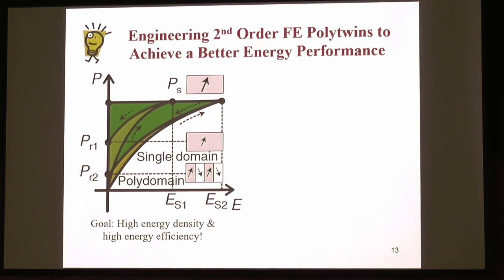But if you begin with a zero apparent polarization, let's say if you have a head-to-tail polydomain structure which is stable at zero field, then when you go pull them, it's going to be really difficult to pull because this is stable. Then after you use a really large field to pull them into about the same direction, you basically charge the capacitor with a lot of electric charges.